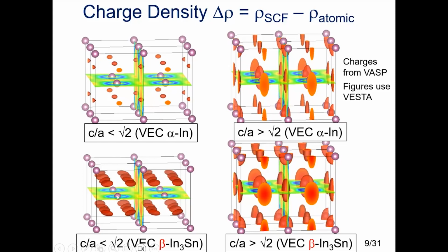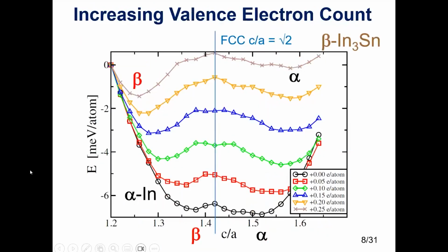So it tells us that there are covalent bonds connecting the body center to the atoms in the plane above. Those covalent bonds will try to reduce the C axis and keep the C/A ratio low. Okay, so I think that these different patterns of covalent bond formation are probably the origin for the relative energies that we saw in these figures.